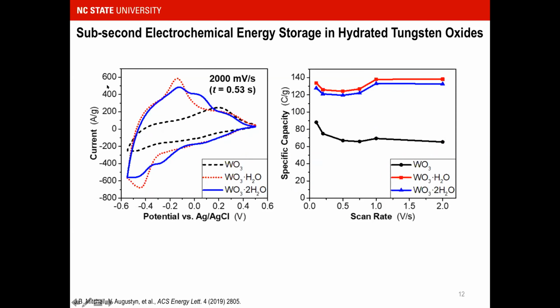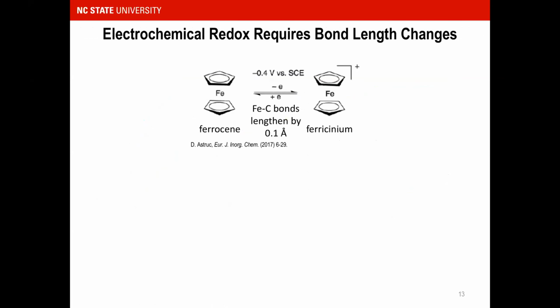And these are cyclic voltammetry curves where we're comparing the 3 different phases: the anhydrous tungsten oxide, and then the hydrated ones. And what you see, the reason why I say we have this really exciting performance, is that the area enclosed by the hydrated phases is higher, meaning that you have a higher specific capacity. And this behavior is true for all of the scan rates we investigated, and here these were particularly fast. Also, the electrochemical reversibility is very high, meaning that the energy efficiency of this electrode would be high.